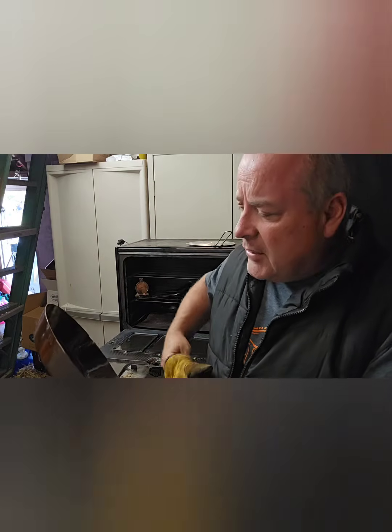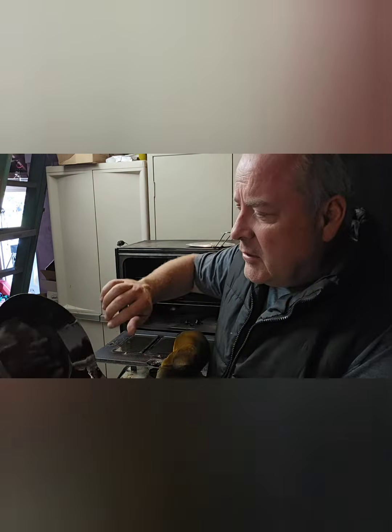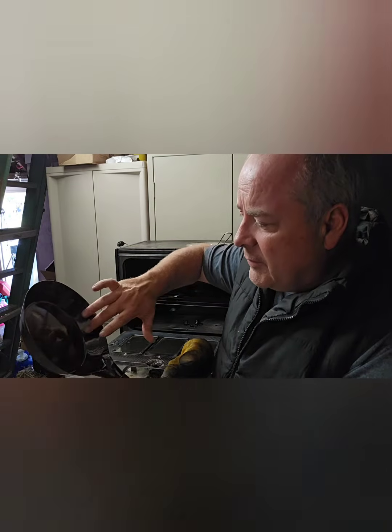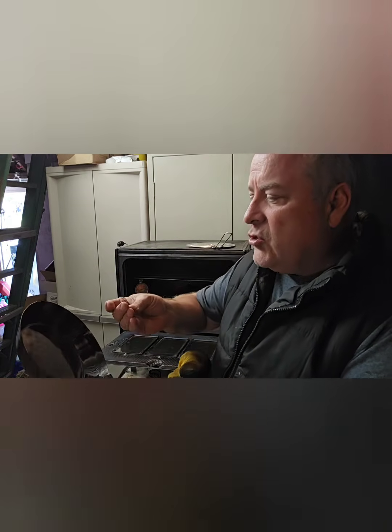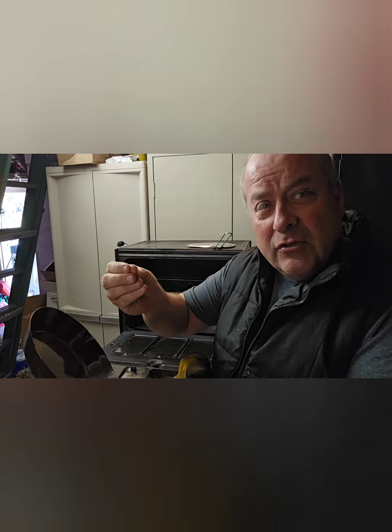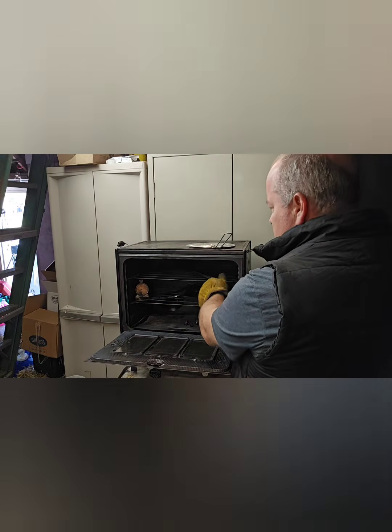You can typically touch the pan. Obviously I wouldn't recommend you use your bare fingers, but my hands aren't that sensitive to heat because I'm constantly grabbing these hot items, but it should come away feeling like glass, but no oily residue and certainly no stickiness. There should not be any sticky residue in the pan. We want a glass-like finish, and we know that that's a perfect season. Any tackiness means that the oil has not fully polymerized.